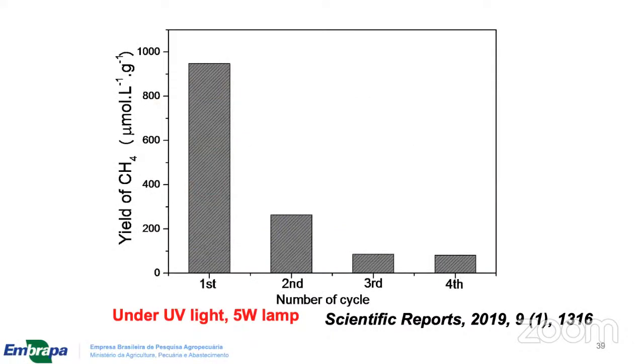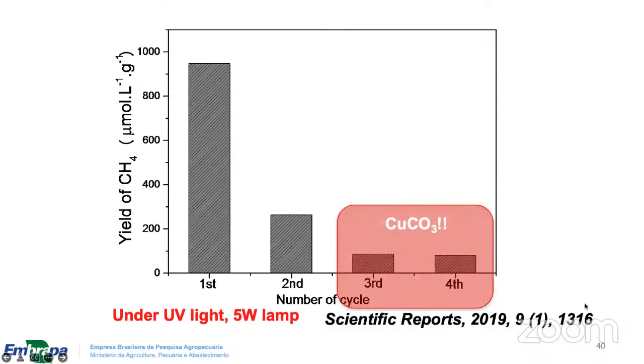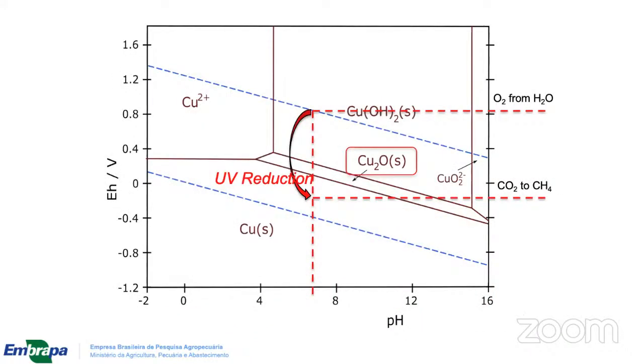Taking different cycles over this best system, we got a significant production of methane, but on the other hand, this production is going down so fast. This production is going down by poisoning, making copper carbonate over the surface, as we have proposed. Again, the light is going to reduce the material, the original copper oxide, to metallic copper, at least at the surface, and making the oxidation of the surface to copper carbonate. So how can we increase the stability of the system?